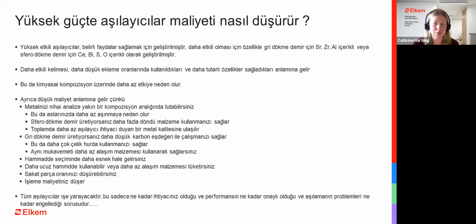This also provides you with an iron that will naturally come from the furnace with an overall lower need for inoculation, so that you can run lower carbon equivalent in your gray iron. That's another way to save cost. That will allow you to use more steel scrap, and will also allow you to use less alloying to achieve the same strength. If you can control the carbide tendency in your gray iron with a good inoculant, then you can work with a lower silicon and lower carbon equivalent in your gray iron. You get your strength from controlling carbon equivalent instead of using alloying elements, and alloying elements tend to be higher in cost than carbon and silicon. So you may be able to use less alloying to achieve the same strength.